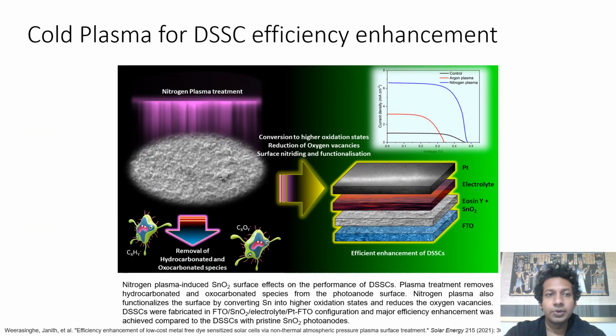Dye-sensitized solar cells, or DSSCs, are a promising and increasingly cheaper alternative to the conventional silicon-based solar cells. In general, DSSCs encompass an electrode consisting of a nanocrystalline photoanode film tailored with a sensitizing dye, a platinum counterelectrode, and an electrolyte solution in between the photoanode and the counterelectrode. We use plasma-treated tin oxide photoanodes to fabricate dye-sensitized solar cells, and a remarkable five-fold efficiency enhancement was achieved with the single-step surface treatment of photoanodes.